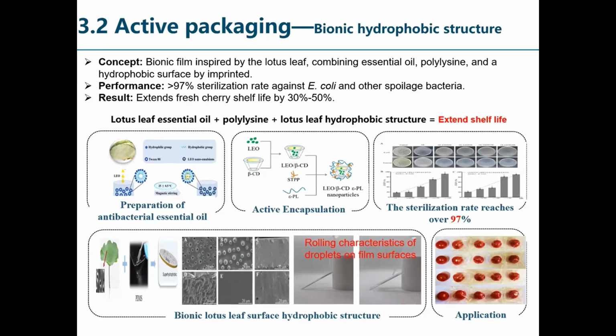The film achieves a sterilization rate of over 97% against common spoilage bacteria. The microstructure repels water droplets, just like a lotus leaf, keeping the package film separated and not contaminated. This superior preservation capability leads to an extension of the shelf life by 30% to 50% for fresh cherry.